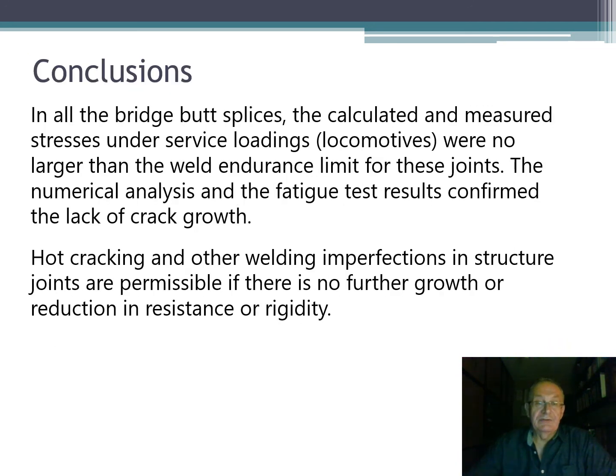And conclusion: in all the bridge butt splices, the calculated and measured stresses under service loading were not larger than the weld endurance limit for these joints. The numerical analysis and the fatigue test results confirmed the lack of crack growth. Hot cracking and other welding imperfections in structure joints are permissible if there is no further growth or reduction in resistance or rigidity.